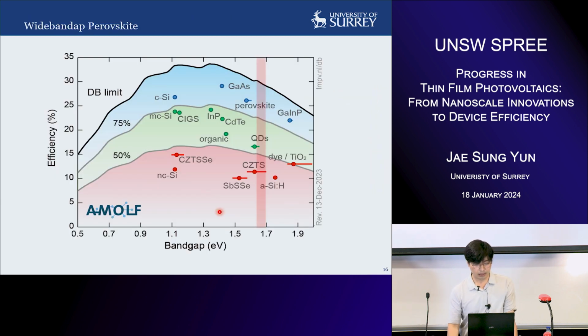So the electrons just move to the narrow band gap where it is supposed to create voltage. So as I mentioned, the perovskite cells have a very good efficiency when it's in narrow band gap. So the efficiency deficit is quite small, if you see around 1.55 eV perovskite. However, when perovskite has a large band gap for tandem purpose, the current status of the efficiency is only around 20%.